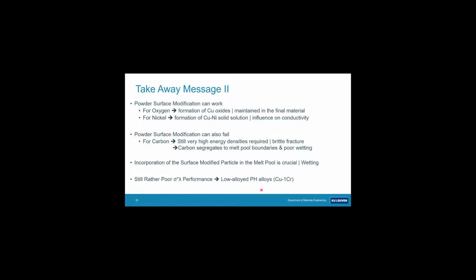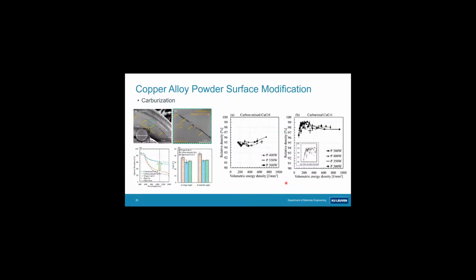So instead of starting from pure copper, we started to play with a low alloyed copper 1% chromium powder. And also there we applied surface modifications, because that powder itself still has a fairly low absorption, because 1% of chromium does not contribute. But when you carburize, and how did we carburize it? We did not simply coat it with carbon. The first step was coating, but then secondly, we applied a heat treatment, so that chromium actually diffused from the inner side of the particle along the grain boundaries to the surface of the powder, and there chemically bonded with carbon to form carbides. So we also found carbides at the outer surface of the particle.